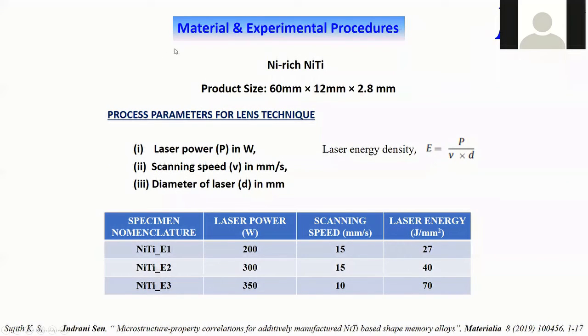We use the same powder and the same design to make a product, but we use three different energies. The one which has the least is 27 joule per millimeter cube, and the highest one uses 70. And we name these E1, E2, E3. So we are starting with the same powder. We are just varying the processing parameters of the additive manufacturing to end up having three different products.